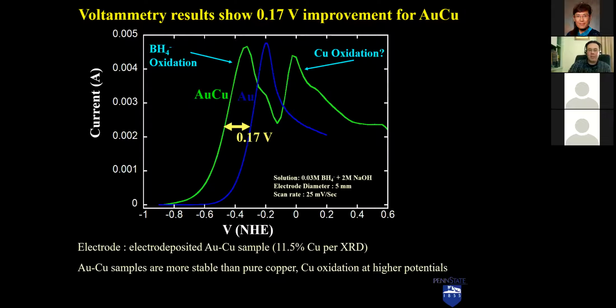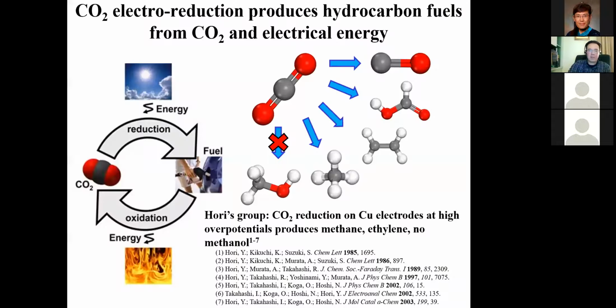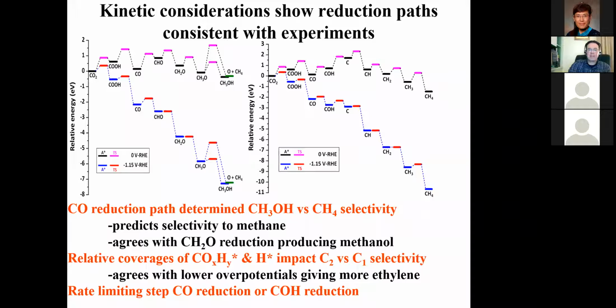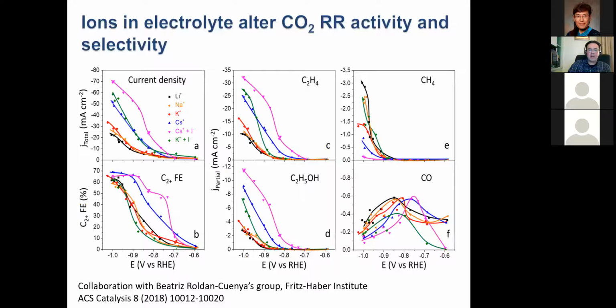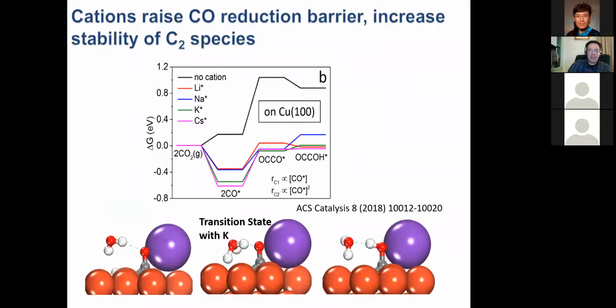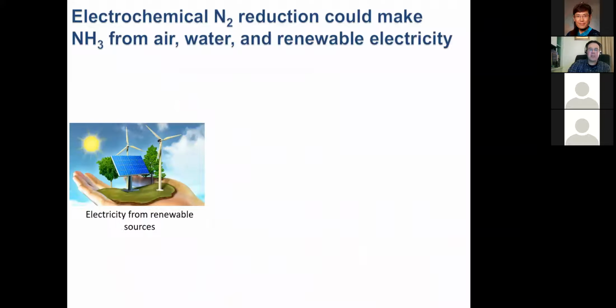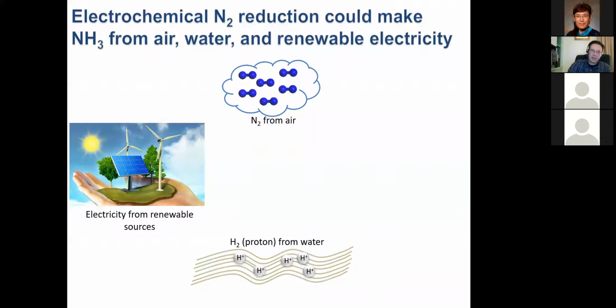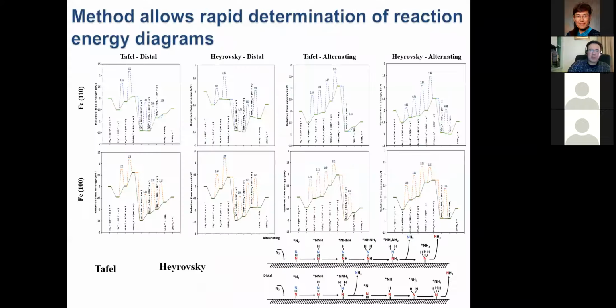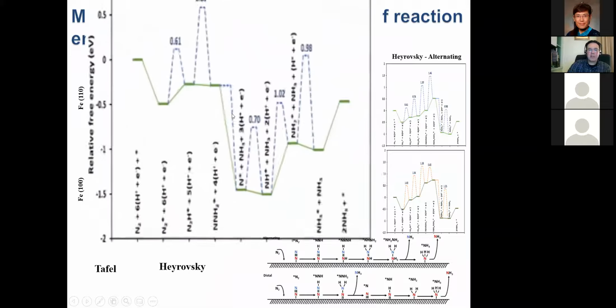And again, I'm going to have to hit page down quite a bit now, because I knew I wouldn't have time to walk you through doing the same thing for carbon dioxide electroreduction, where we can map out those reaction energy diagrams, DFT calculating barriers, look at how cations are involved, put that in the model, and try to explain how they change the CO2 reduction energetics. We can look at ammonia, which is not a pretty story from our results because all these barriers are really big. You see a lot of 1 eVs showing up there for barriers.